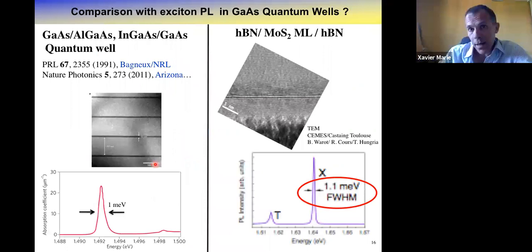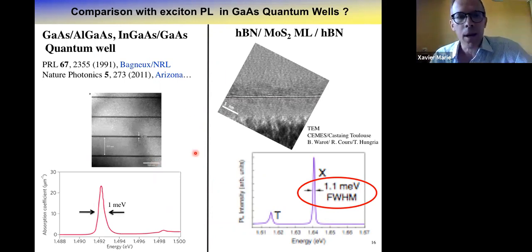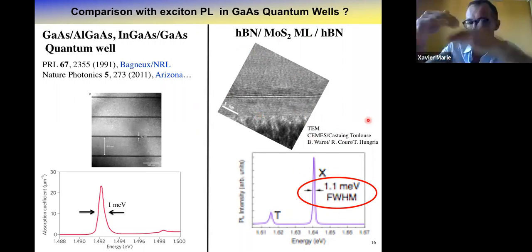It's quite amazing. Like some people, I work and still work on III-V semiconductors, where the nanostructures are grown by molecular beam epitaxy, ultra-high vacuum, and you get, for instance, 2D exciton linewidths of the order of millielectron volt with this kind of fabrication technique. You have a cross section here of an indium gallium arsenide quantum well, in dark here, 4-5 nanometers thickness. And here you have this basic van der Waals heterostructure, MoS2 monolayer encapsulated in hBN. High resolution TEM, and the white line corresponds to the molybdenum layer, and all these lines here correspond to the hBN. And you get a linewidth of the order of millielectron volt, though we have used a very, very basic fabrication technique.